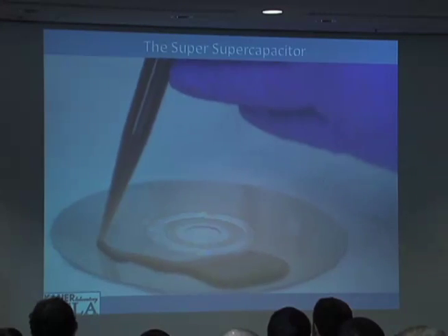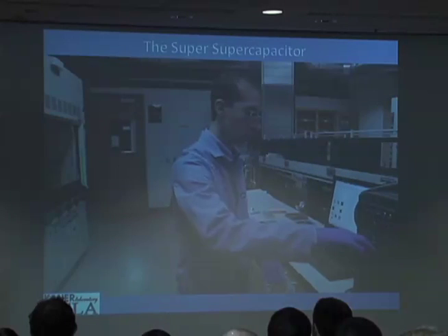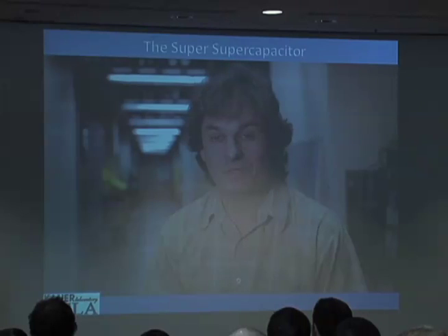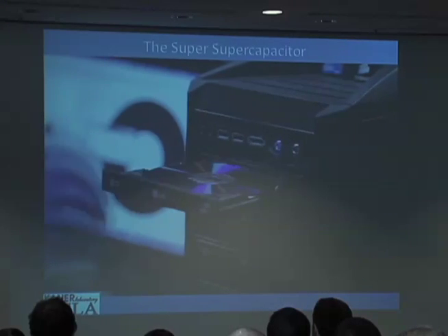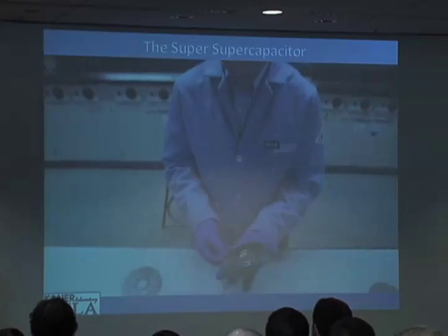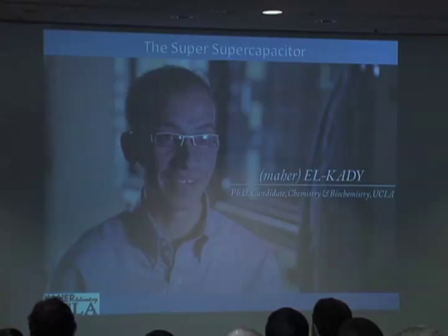We start with graphite oxide, which is a water-dispersible material. We then coat it onto sheets of plastic. We hit it with a light from a laser. It deoxygenates, it turns it into graphene. So it's both very exciting because we made all-organic graphene in a very simple process using a consumer-grade DVD drive that you can find everywhere. But the real discovery was yet to come.